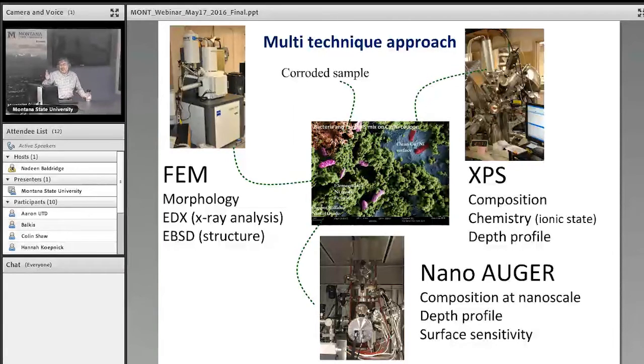With nano Auger, this is, as I said, just being installed. Actually, this system can do all of this and some, but you can also do composition at nanoscale, truly nanoscale, both image and spectral resolution within 4 nanometer accuracy. Depth profiling: we have a very sophisticated $150,000 argon gun. We can do surface sensitive analysis.